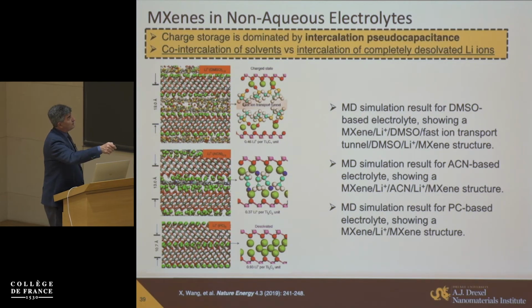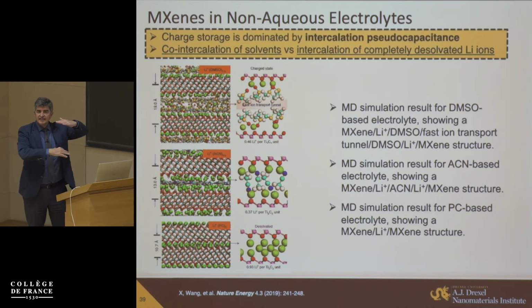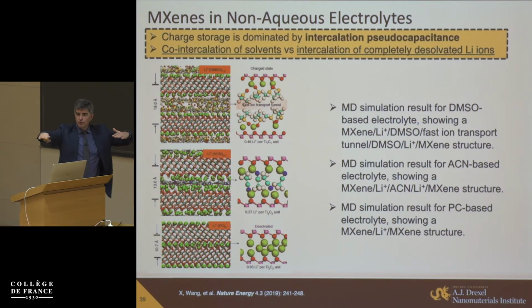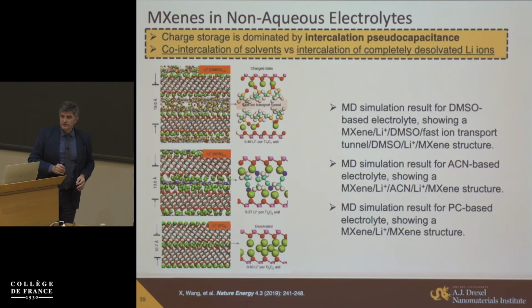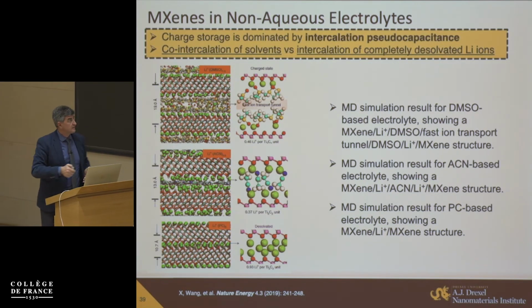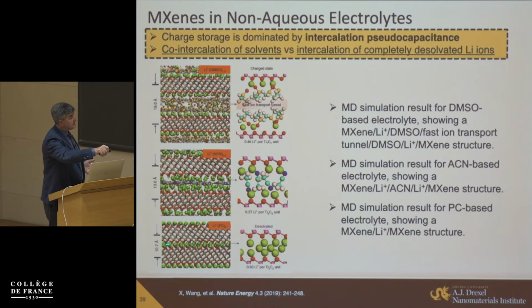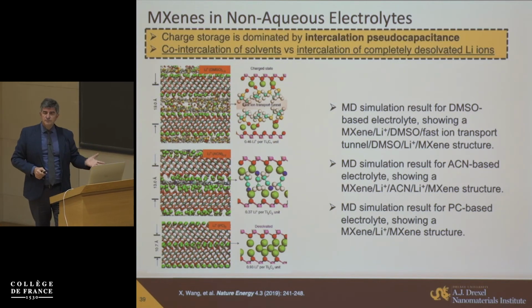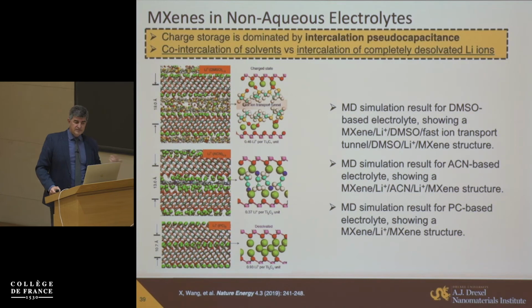In the case of DMSO, as modeling showed, we get lithium and we get DMSO. Moreover, lithium stays somewhat solvated. Some lithium ions go to the surface here. In the case of acetonitrile, which shows the worst behavior, lithium and acetonitrile go in. But actually, acetonitrile separates, it's pushed out in the layer between the sheets. So basically, we get a poorly electronically conducting layer of solvent molecules separating layers of MXene. And in the case of PC, we only get lithium within this space. So we get a fast intercalation of lithium between the layers with complete desolvation, without PC.